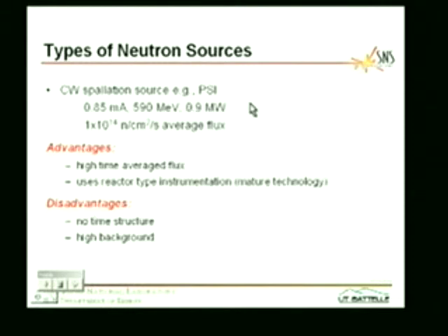So this is more like a 10 megawatt research reactor. It's actually like a 10 megawatt heavy water research reactor in terms of the neutron flux. So it's about 10 to the 14 neutrons per square centimeter per second. So with this continuous source, you have a higher time average flux than you do on the pulse source.